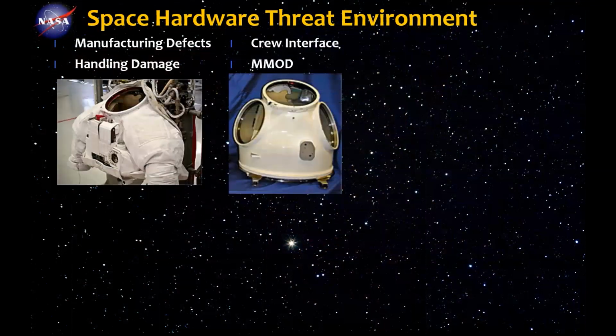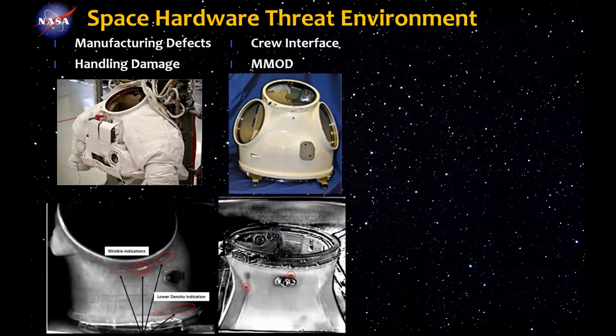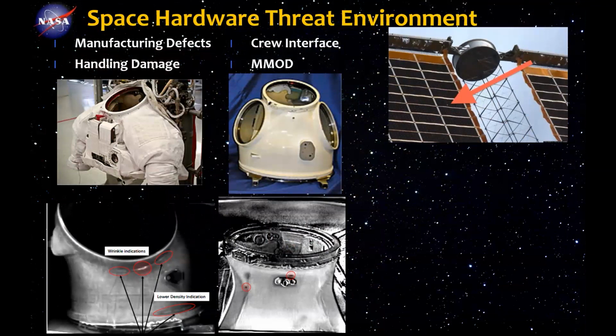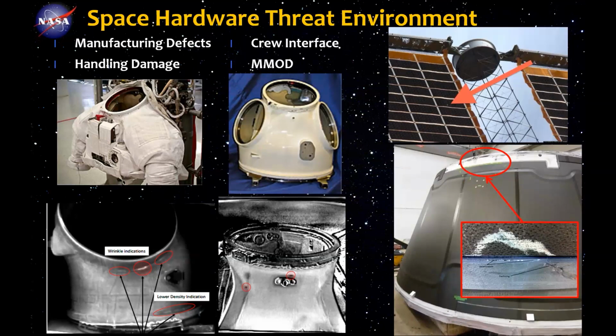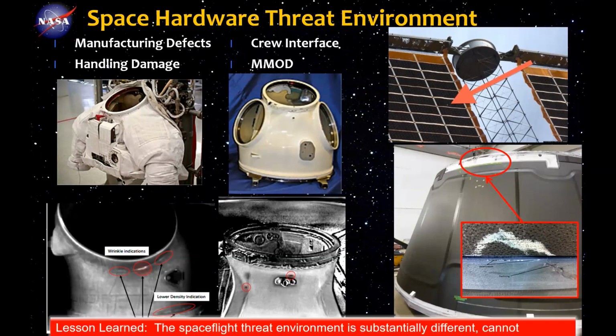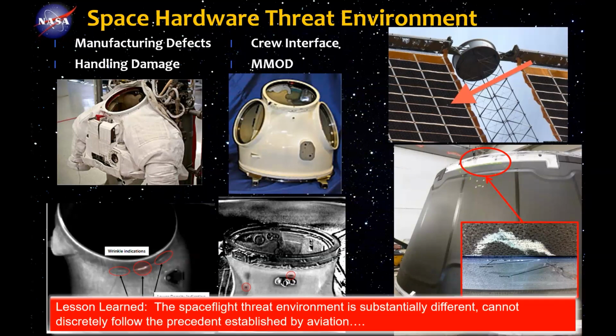When we think about damage tolerance, I'm thinking about an astronaut getting in and out of a suit and banging their head on the side of it, or setting it down in a rough way and banging it around a little bit, right? But even then, knowing it's a spacesuit, they're going to be gentle with it. In space, we actually lost one of the ammonia loops on the space station because space junk flew through one of the radiator panels and caused a delamination of a composite sandwich, which caused a thermal problem. We had to isolate that particular ammonia line on the station.